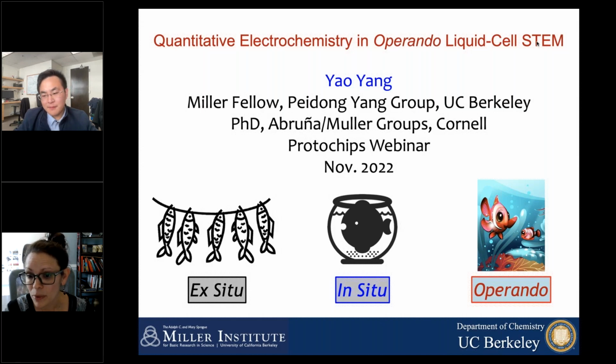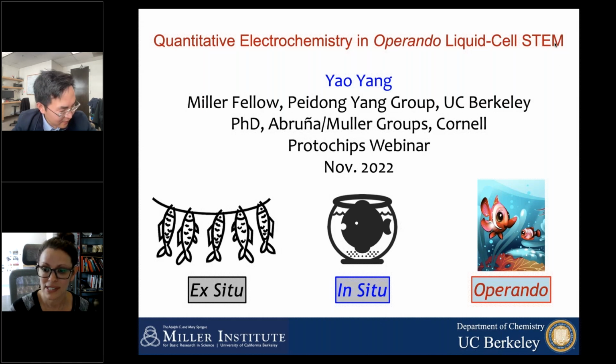I have been sweeping the working electrode between negative 0.25 volts to 0.75 volts versus an SCE in a rotating disc electrode, an RDE. But the half-wave potential is around 0.7 volts, and when I read the literature, it looks higher. The ink preparation is fine, but I don't know why the half-wave potential remains low. Do you have any thoughts?